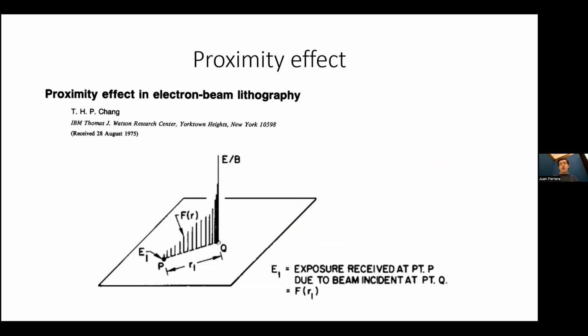So people ran into this problem pretty early on, and they also devised a solution. So here's a paper from 1975 by Philip Chang, where he recognized that there is a point spread function, so that if the electron beam hits at this point, there's going to be energy deposited at a separate point, and the energy being deposited at the point P just depends on the radial distance between Q and P. So they recognized that you can build a point spread function, which is this function here, and all you have to do is convolve it, and then that'll tell you how much energy is being dissipated.